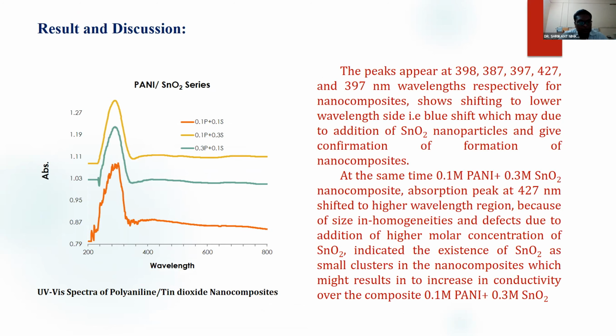So as you see in the UV visible spectra, from that spectra I'm concluding that there are some peaks observed at 398, 387, 397. These are the peaks which are to be observed in the polyaniline structure. But due to the addition of SnO2 nanoparticles, SnO2 metal oxide, these peaks are shifted towards the lower wavelength, that is a blue shift you can say.